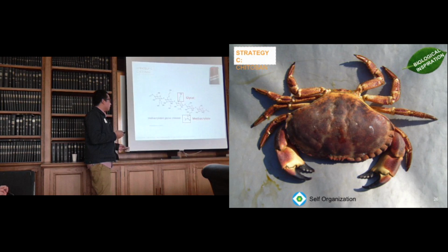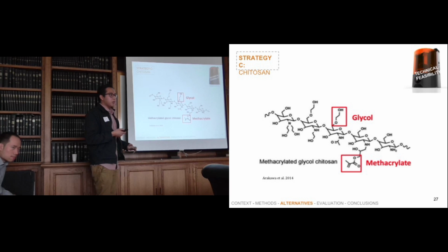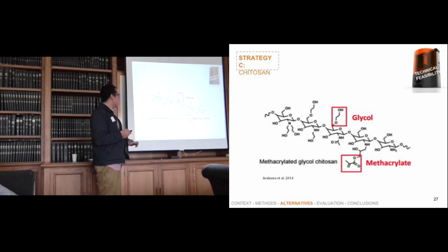This slide is to illustrate what MGC looks like. In addition to being biodegradable, biocompatible, and relatively safe for humans, chitosan is also relatively insoluble. So the only way you can solubilize it is by using an acidic solvent or by adding a glycol group to its backbone. Once you add the glycol group to the chitosan, it becomes soluble at pHs of greater than 7. And the main reason why you want to solubilize chitosan is so that if you want to graft the methacrylate group by using either methacrylic anhydride or glycidyl methacrylate, you need to solubilize it.